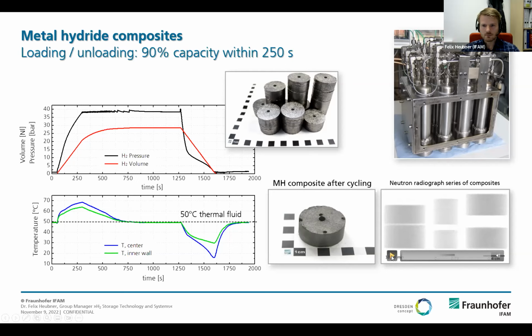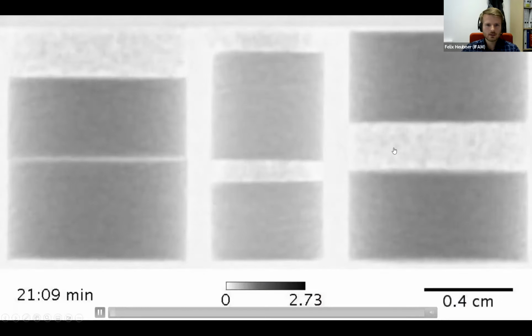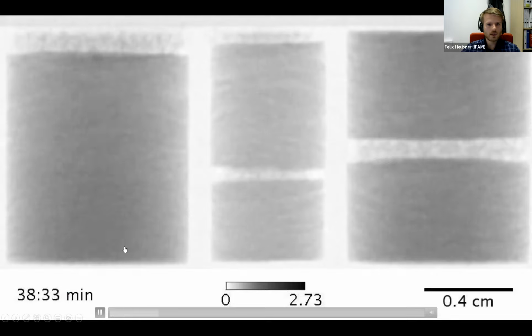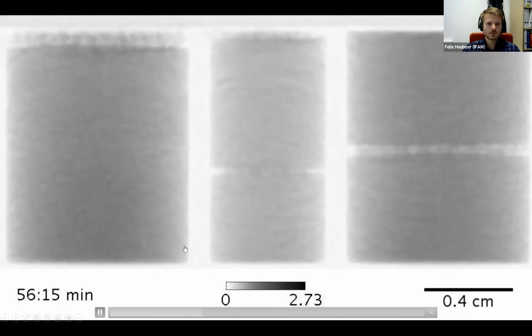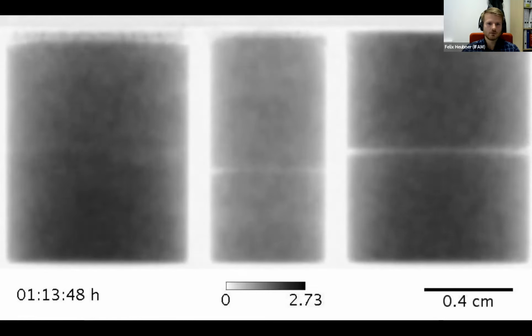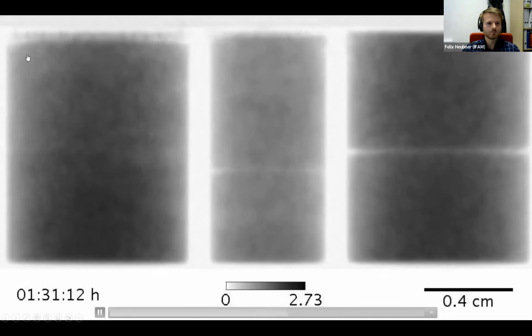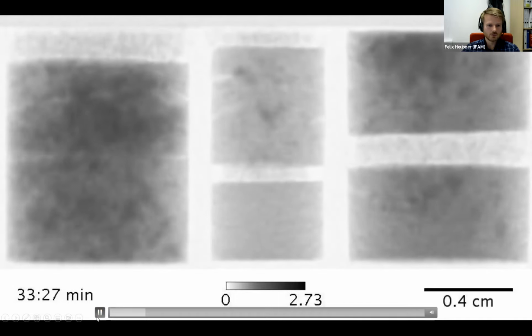So I want to show you again a radiograph series of materials that are absorbing and desorbing hydrogen in a cyclic behavior. And it's a neutron radiograph series. So the darker the radiograph is in the area, there's more hydrogen because you have a high interaction between neutrons and hydrogen. So black means hydrogenated state, gray means dehydrogenated. And I'm starting right now. This is hydrogen absorbing material on the left, on the middle, and on the right. And it's absorbing now in a few seconds and desorbing again in a few seconds. And you can see, for example, the volume expansion during absorption and shrinking during desorption. And the darker regions are highly hydrogen filled here in this case. And the light gray regions show you the dehydrogenated states.